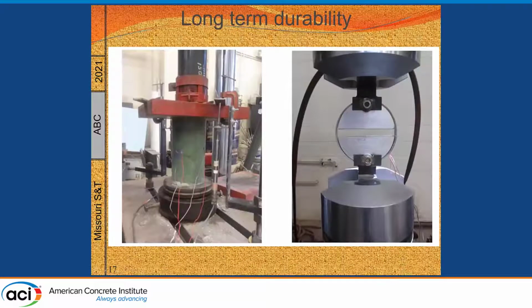Once we subjected the columns to the severe weather, we took those cylinders and did two different types of testing. On one test, we did cyclic load on the cylinders to determine how the environmental conditions affected not just the strength, but also the deformation capacity and the energy dissipation of the cylinders. We had two sets of cylinders. For one set we used epoxy resin. Epoxy resin is quite expensive, so working with DOT engineers who would like a cheaper option, we also did some cylinders with isopolyester resin, which is much cheaper than the epoxy.